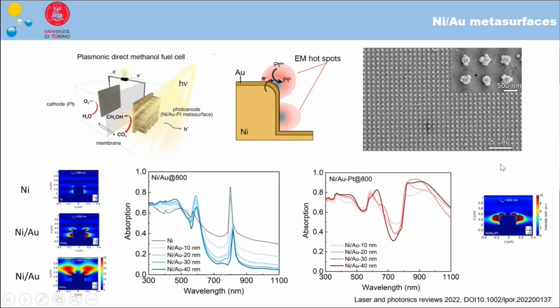And here you can see that we can achieve different effects, different resonances of the nickel gold pillars. We can have broadband absorption due to cavity modes or hybrid cavity SPP modes, or we can also have hybrid resonances, which are due to the surface lattice resonance, basically where the diffractive modes of the nickel couple with the localized surface plasmon resonance of each individual pillar, and so we can achieve these sharp resonances.